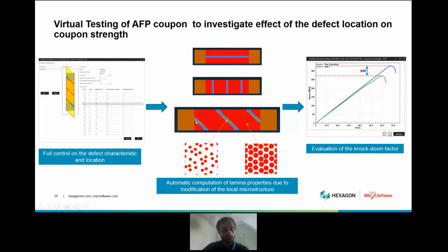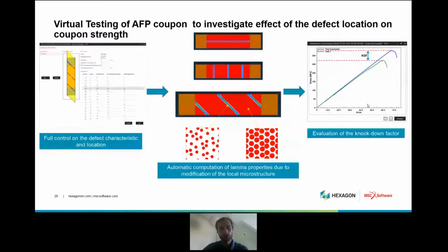So in this example, in the gaps zone, what we have is a lower amount of fibers. That means that the material will be less stiff and will also be less strong in those areas of the ply. And the question is, once I perform a tensile test on this coupon, what is the knockdown factor that I get? And with the simulation approach, you can compare what happens from a pristine point of view, so without any gaps, and when you have the defined gaps, what is the final strength? And this knockdown factor can then be evaluated for all possible defect variations and can enrich the final decisions on how to manufacture the part.